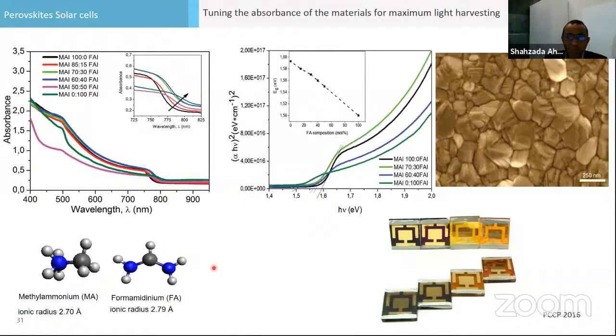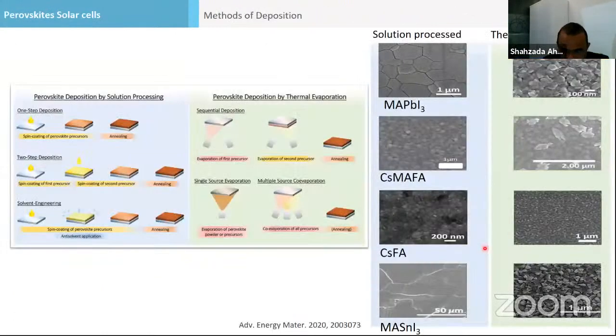This is pure methylammonium iodide, but if you replace iodine with bromide, the band gap is higher, but the cells are very transparent. And these transparent cells are very good for building integrated photovoltaics. But they are not very efficient. They will give you 10% or 11% efficiency, but they are more or less semi-transparent. Orange color, you can see them. So this will be good for other applications here.